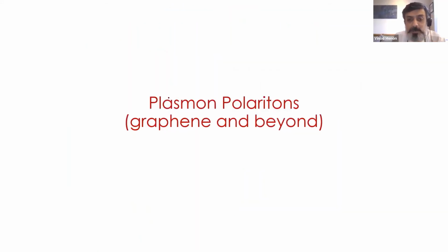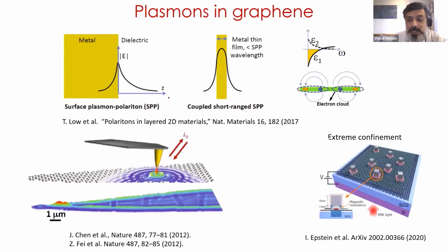So there are also plasmons in these systems. There is a lot of work on plasmon polaritons in these systems where people have looked at graphene. In fact, there's a very recent work where they showed very strongly confined plasmons in these systems because graphene is just one atom layer thick, and so you can get very tight confinement in these systems.